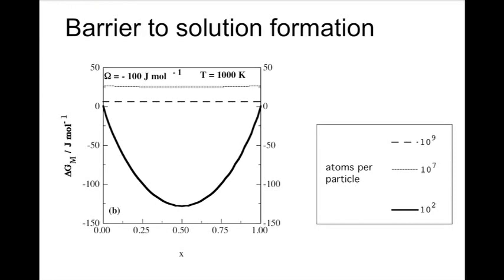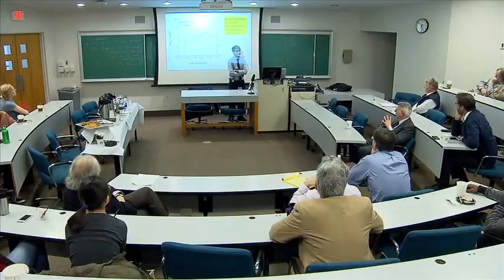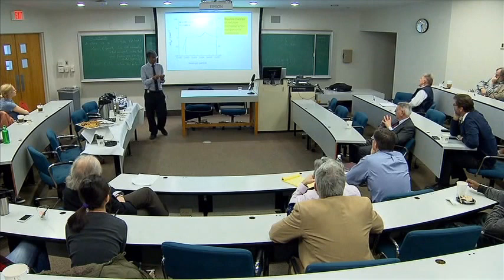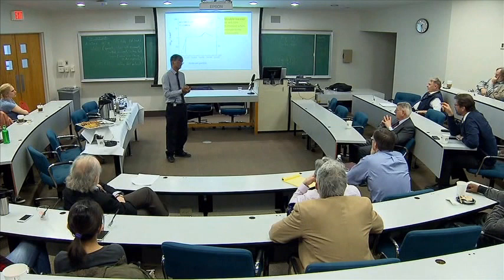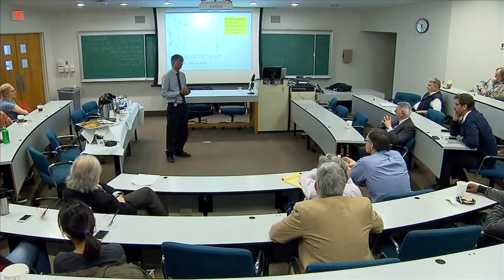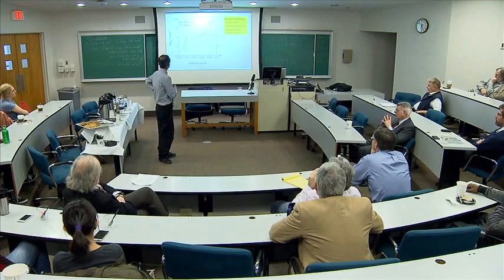There is a hugely abrupt threshold around a particle containing about 100 atoms, and the cube root of 100 is about 5. So there seems to be something significant about 5 atoms in a direction — when you get to an individual atom, there is no concept of an interface. So that transition really happens at a cluster of about 5 atoms in a linear direction, though the actual value will depend on the bond energies used.